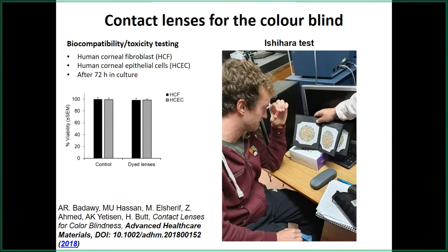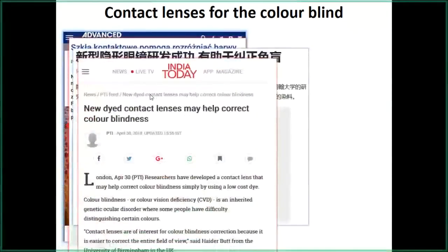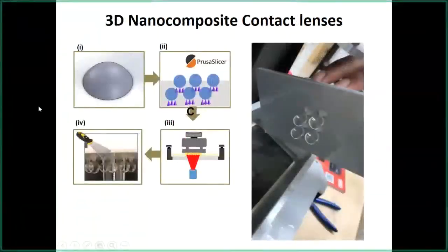Actually, this was a very easy case for us because we were using a commercial contact lens and then just dipping it in a very safe dye. That's how we produced this lens, so it was safe, and the results were very good. This was the control sample, this was our dye, safe, non-toxic. Now in the 3D printed sample, we were just 3D printing this, using a very safe resin from our site. And then when we did the toxicity testing, these samples were killing all the cells. We were very surprised that these lenses could be toxic, and we thought that the lab had some issues.